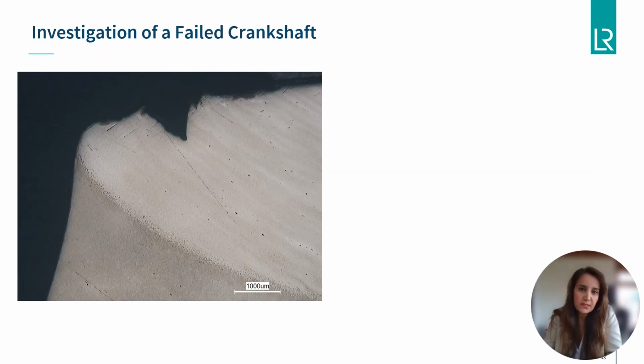A section was taken through the areas of spalling and the initiation area. The sections were mounted, ground and polished to a 1 micron finish before they were etched in a nital solution in order to reveal the underlying microstructure.